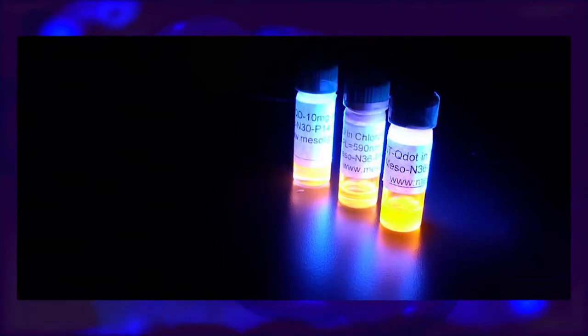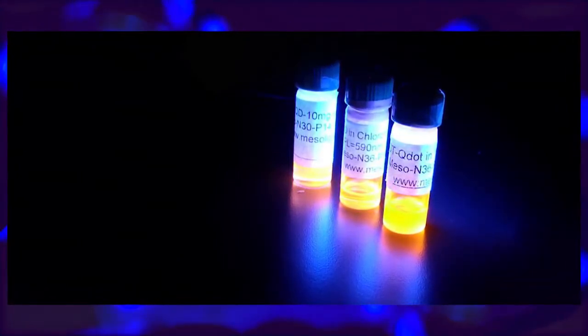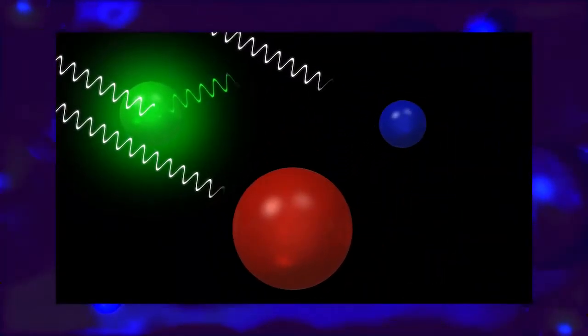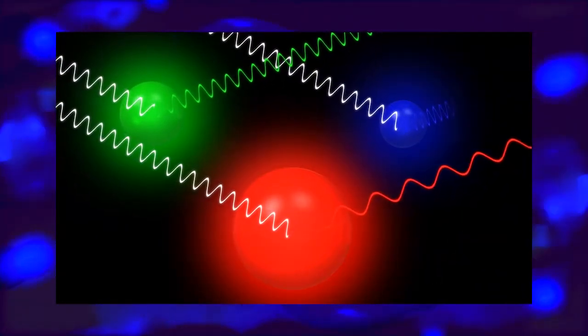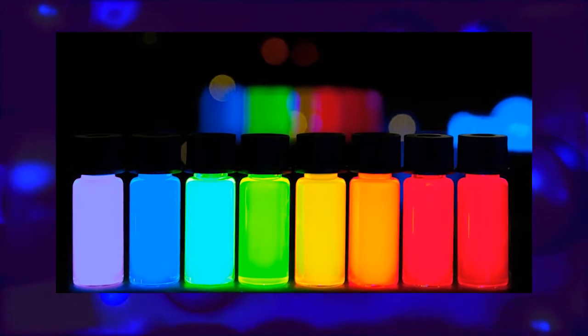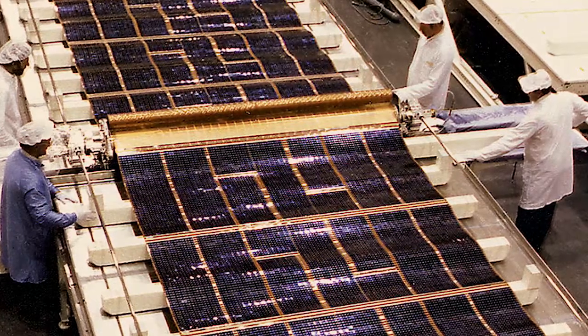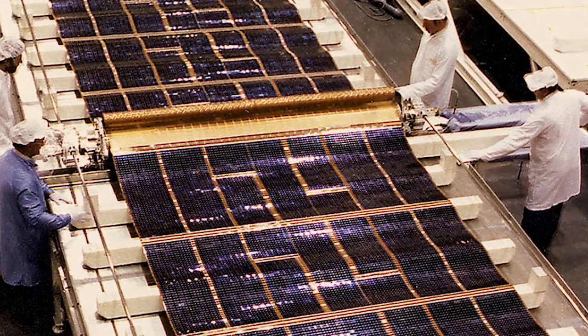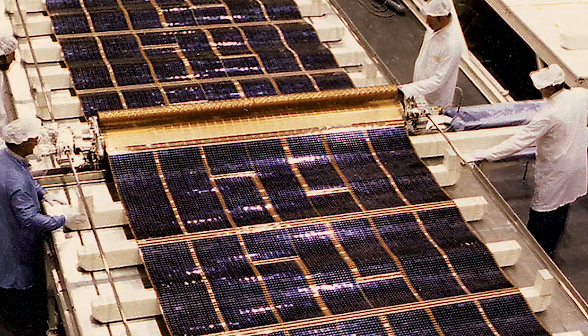Over the last couple of years, people have started looking at originally dye-sensitized solar cells, and now they've moved into quantum dot sensitized solar cells. And one of the major issues that you have with these types of solar cells is they will blend a charge-carrying particle, which is usually something like titanium or tin oxide, with a quantum dot material that could be cadmium selenide, lead sulfide, something of those natures. When they do this, they just kind of mix them and then they put them on a surface, and hopefully they get something that resembles a nice structure. But because they're not pre-planning this, the structure that they ultimately end up with is somewhat haphazard, which leads to a lot of inefficiencies within the solar cell itself.